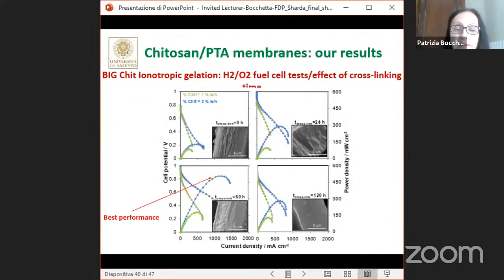Here I show you the effect of the post-cross-linking time, and you can see that the polarization curve and power output are related to two different chitosan concentrations and different post-cross-linking times. It can be seen that the power peak increases as the cross-linking time grows up to 60 hours, and afterwards slightly decreases. This data agree with EDX data showing that a time of 60 hours is required to complete the cross-linking process. As shown in all the recorded polarization curves, kinetics is mainly governed by the ohmic overpotential, mainly attributed to the membrane proton conductivity.